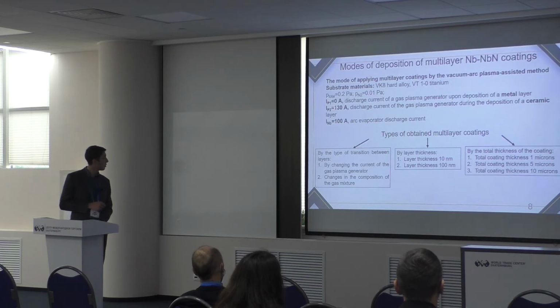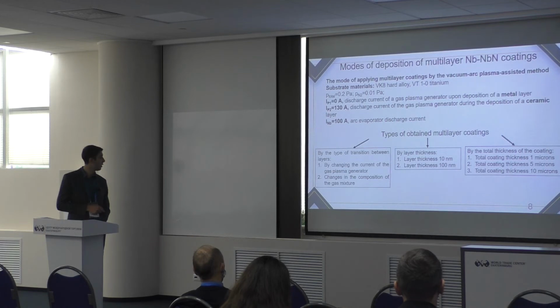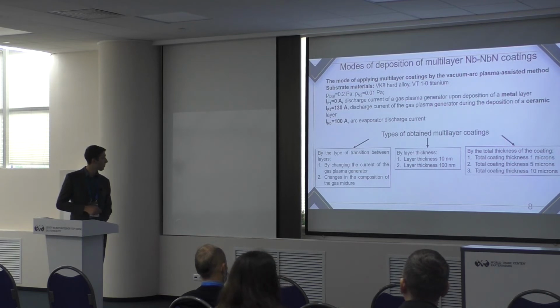To get the nitride coating, we powered on the gas plasma generator, and to get a metallic layer, we powered off the gas plasma generator. In plasma-assisted modes, several types of niobium nitride coatings were obtained with different layer thickness, such as 10 nanometers and 100 nanometers. We varied the coatings by changing the current of the gas plasma generator and changing the gas mixture. The total thickness of these coatings was 5 micrometers.